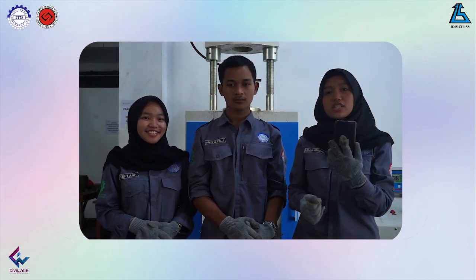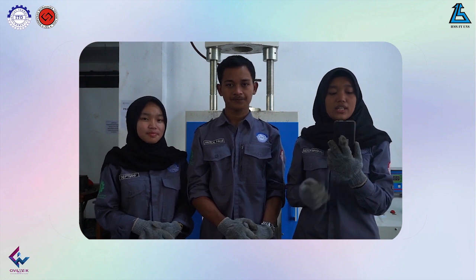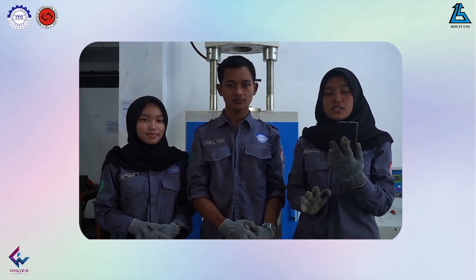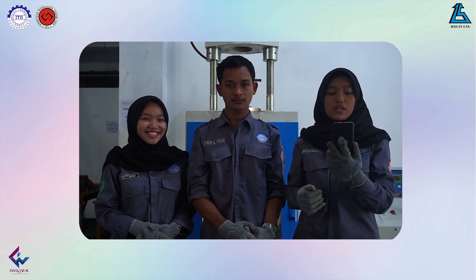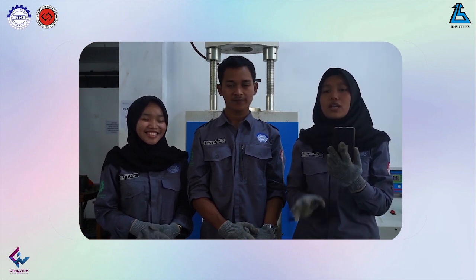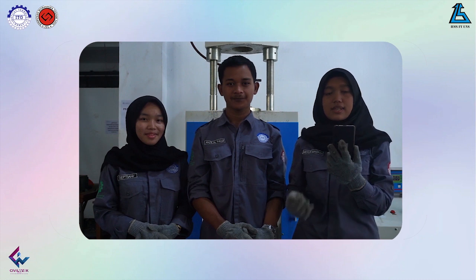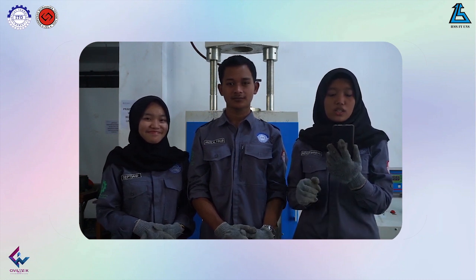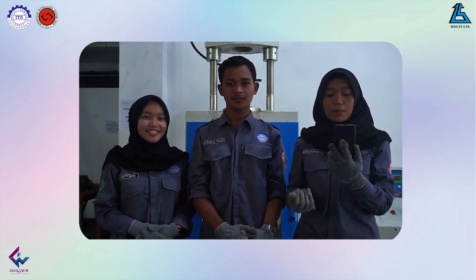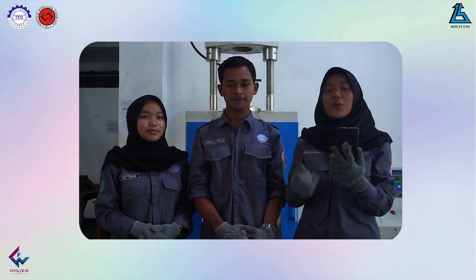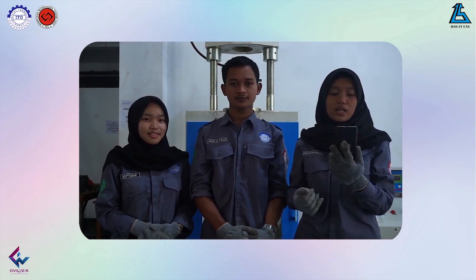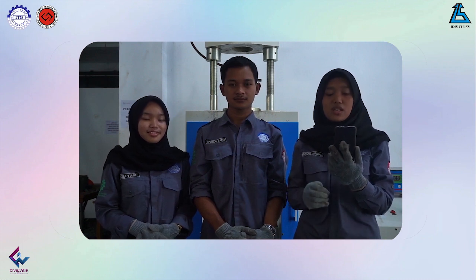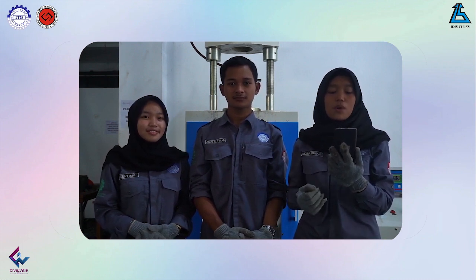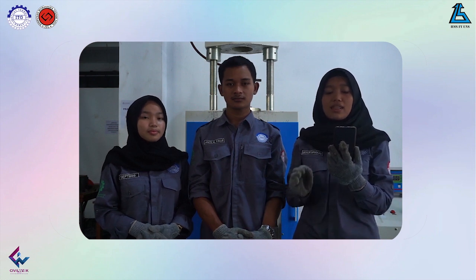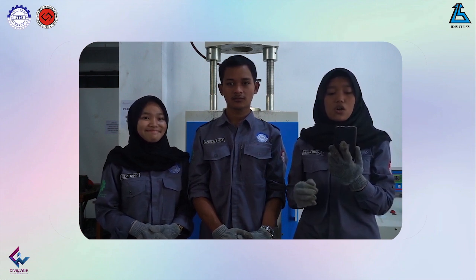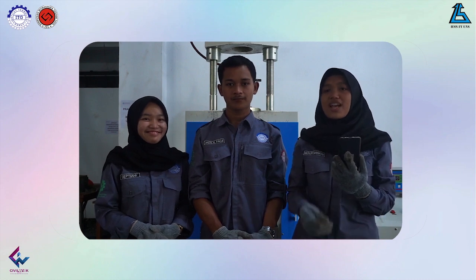After the concrete reaches the age of one day, the concrete needs to be tested for compressive strength. The target compressive strength is a minimum of 15 megapascal. Concrete testing steps include removing the one-day-old concrete from the mold, preparing the machine for the compressive strength test, putting the concrete on the compressive strength test machine, starting the engine and performing the compressive strength test, and the last, recording the results of the compressive strength test. Let's start.